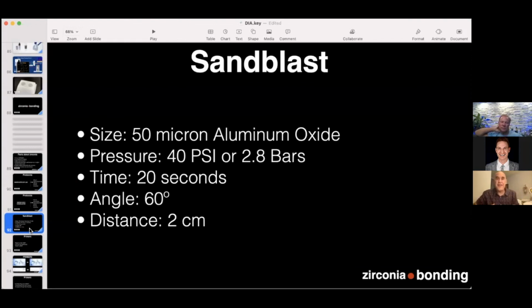Aluminum oxide, 50 microns. Your pressure should be 40 PSI or 2.8 bars. Now, when it comes to time, angle, and distance, those are negotiable. Why? Because when we bond to zirconia in our lab, we bond to a specific area, but you are bonding to a crown that is very, very customized to the prep you have. So you can't really say that you're going to need 20 seconds to sandblast. Maybe you need more, maybe you need less. What you need to see is that the surface is 100% matte, opaque, okay?